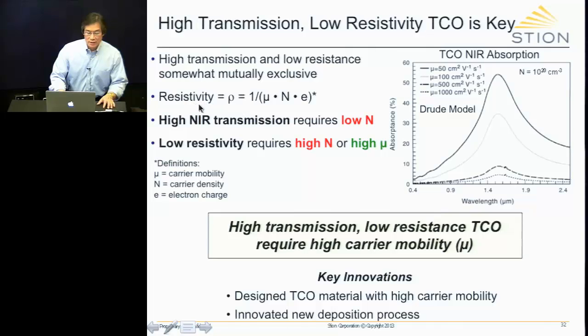The clue is right here. The resistivity is given by 1 over the mobility times the carrier density times the electronic charge. Now again, to get to high near-infrared transmission requires low N. But to get to low resistivity requires high N or high mobility. So the way you counteract these two is to get to very high mobilities, extraordinarily high mobilities.